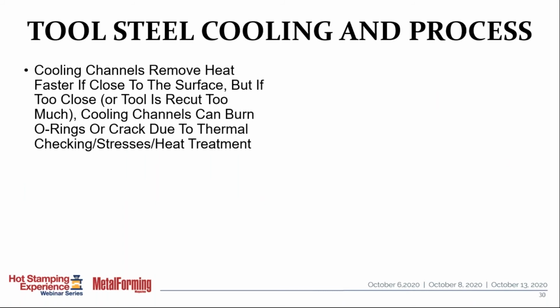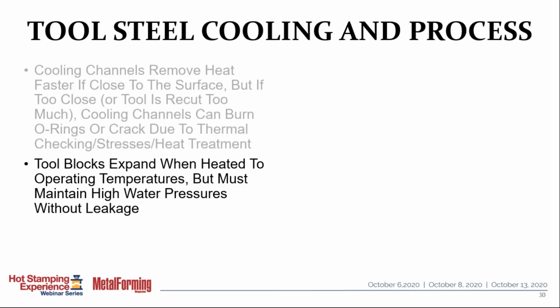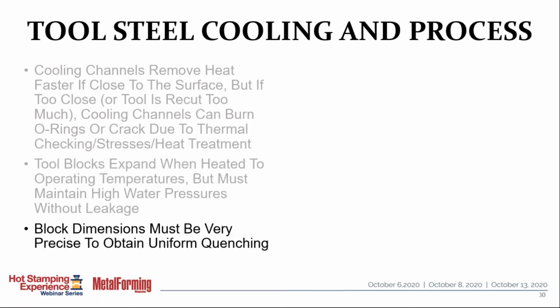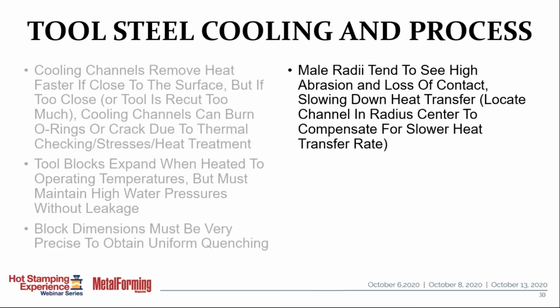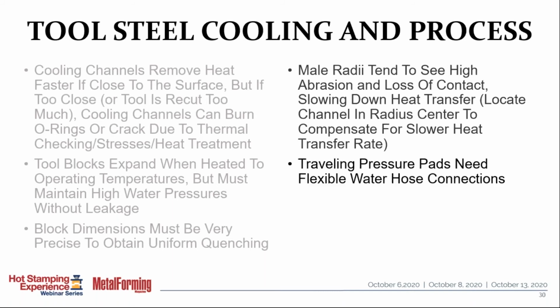You have to be careful not to get too close to the surface. You have to allow for expansion of the tool without creating water leaks, and the machining has to be extremely precise. That's one of the reasons we got involved in it, is it used our skills in precise 3D cutting. There's a lot of wear on the male radii in the tools, and that slows down the quench. And so there's things that have to be done to compensate for that.